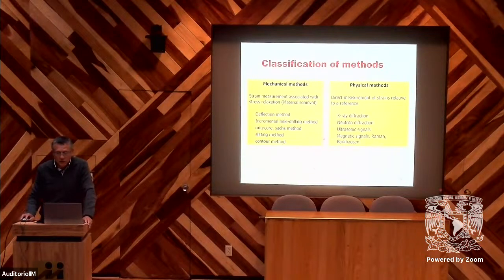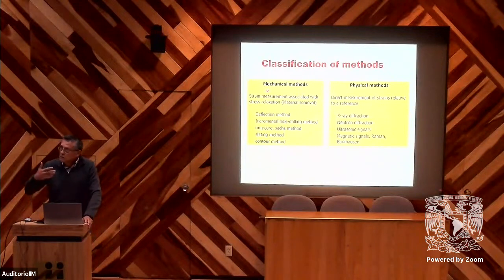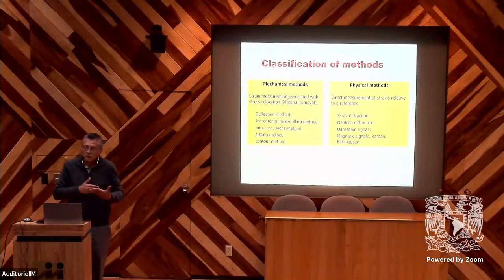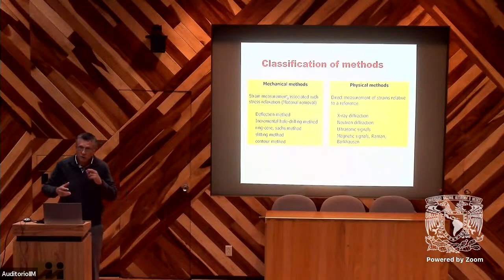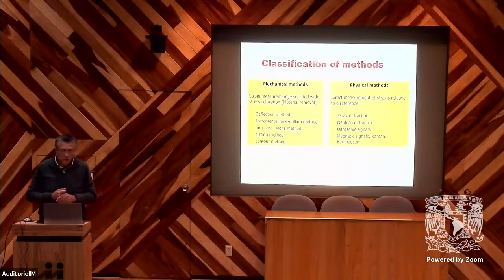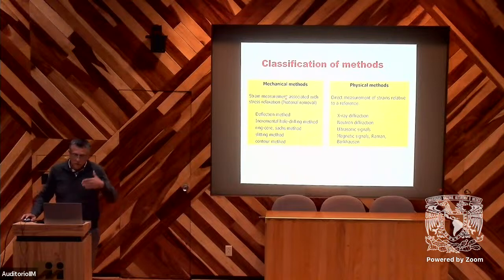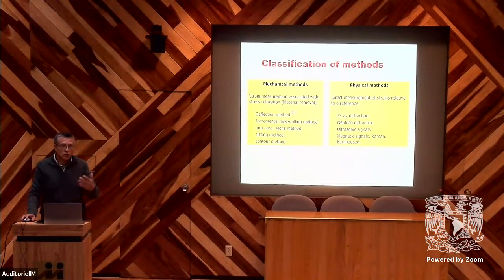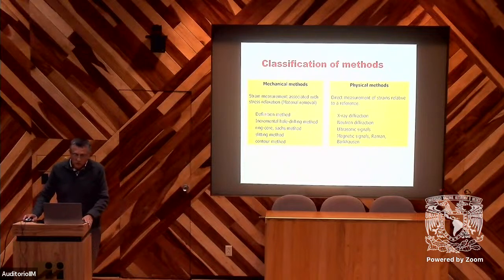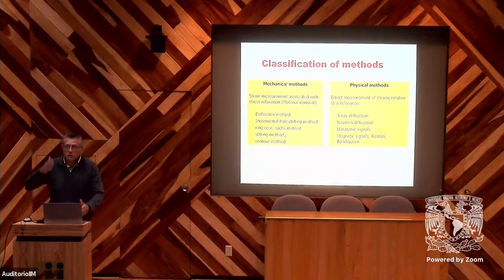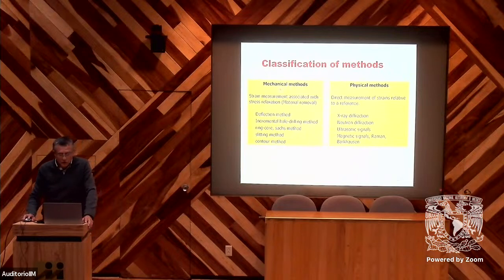So, if we consider the different methods, we will find the mechanical methods. They are destructive methods, and the principle is to remove the material and we see what happened. That means we see the effect of the relaxation of stress. We measure the distortion due to this removal of material. The measurement can be done by different methods, by gauge or by other methods. And we have, for example, the deflection method, incremental hole drilling method, the Sachs method, slitting or contour method. We have some different methods, and also we have physical methods.